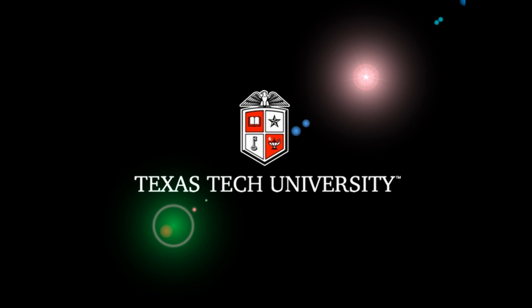As in the case of the longest relaxation time, reptation theory predicts that the viscosity is also proportional to the molecular weight to the third power. Also, in this case, most experiments show that the dependence on the molecular weight is to the 3.4 power.